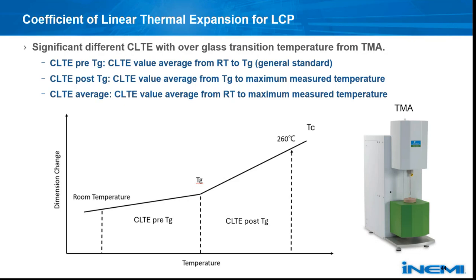So to verify the CTE effect, 3 different CTE value calculation approaches have been investigated. The CTE pre-Tg means the CTE value by average expansion change from room temperature to the glass transition temperature. And the CTE post-Tg means the CTE value by average expansion change from the glass transition temperature to the maximum measured temperature. And the CTE average means the CTE value by average expansion change over the whole measured temperature range. Next.